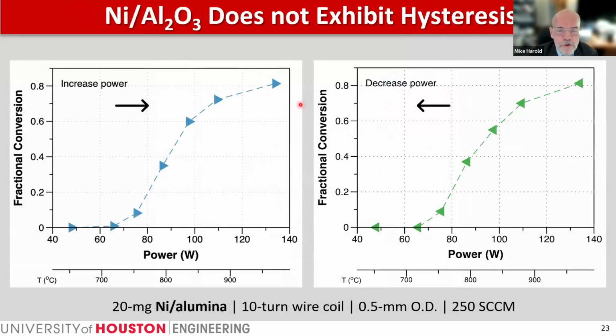Now, let me show you a few more observations in Elmer's set of experiments. We decided to compare the zirconia catalyst support to alumina, which is actually a more conventional support for steam methane reforming catalysts. Interestingly, when we carried out similar experiments with the FeCrAl wire, now coated with a nickel alumina catalyst with the same amount, whether we increase power or decrease power to that coated wire, we do not see any weird ignition, nor do we see multiple steady states. So a notable observation here is that the support does matter, and it is playing a role in these interesting observations that I've presented to you so far.